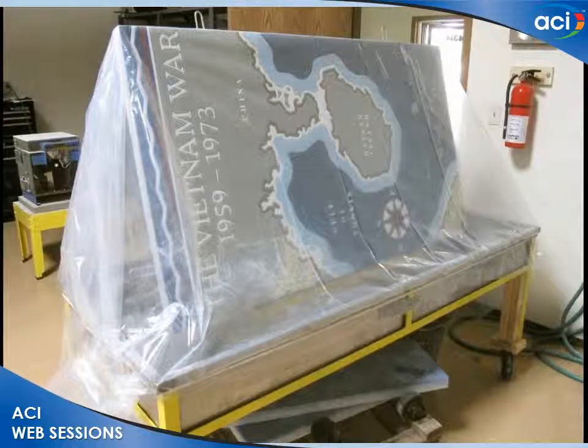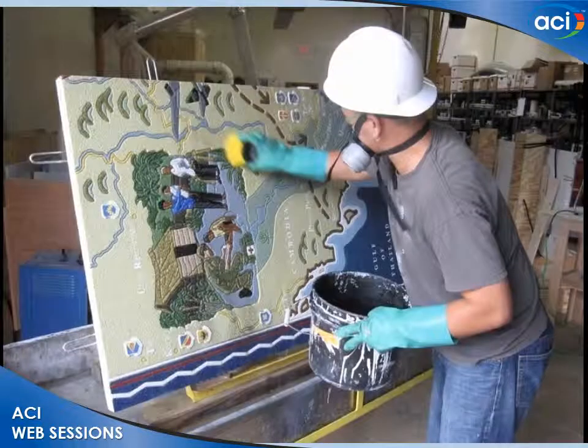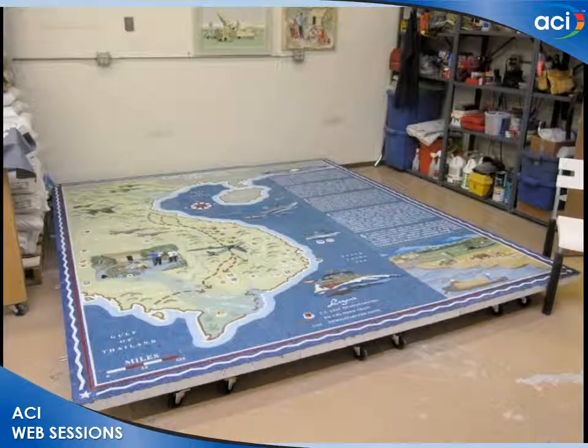Our curing was to wrap it over the stainless steel tub, which had some water in it, and go through 7 days of moist curing. On the second day, we'd pull it out and do that weak acid wash, and that removed the cement film. It's not exposing the aggregate, but it's taking off a little thin haze. Put it back in for wet curing, then 7 days of dry curing.